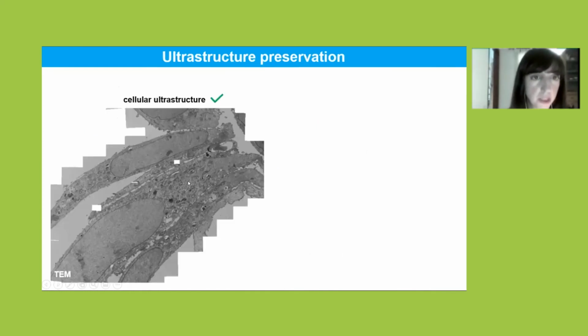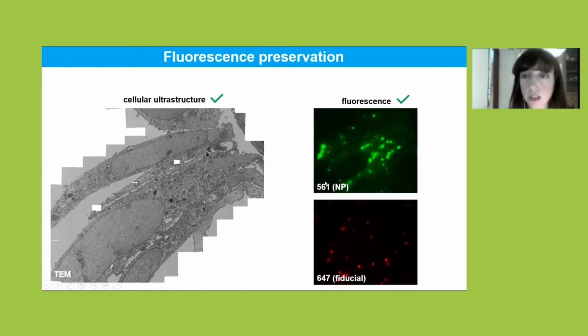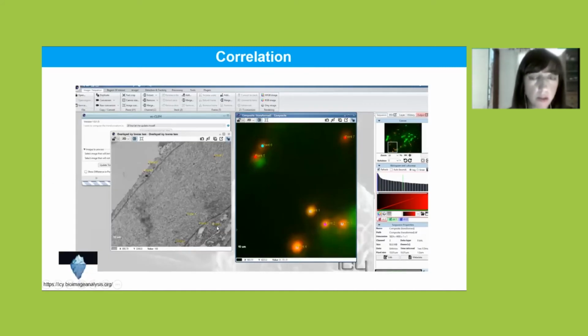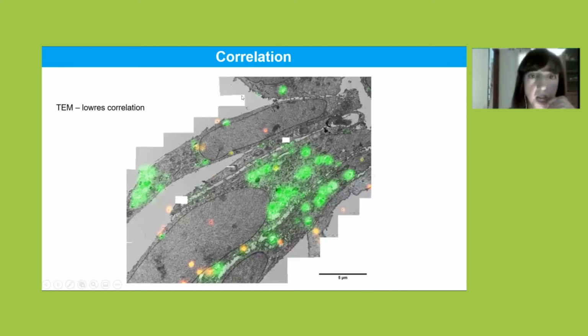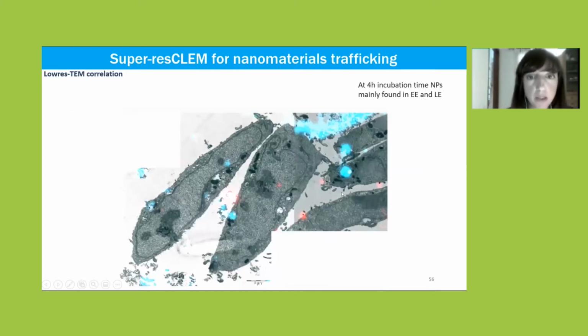So as I told you, it's very nice ultrastructure, as you can see here. The fluorescence is very well preserved. So this is the channel of the nanoparticles. So these are the same nanoparticles that we used in the in vitro correlative method before, no? So these polymeric nanoparticles. And then the fiducial marker to be able to do the correlation of both images later on. We are using ICY software, that is a semi-automatic software to get the correlative images, and then we get this type of images. In this case, it's with low resolution. This is for 4 hours.